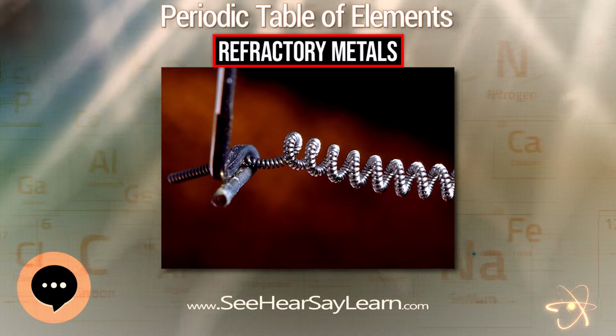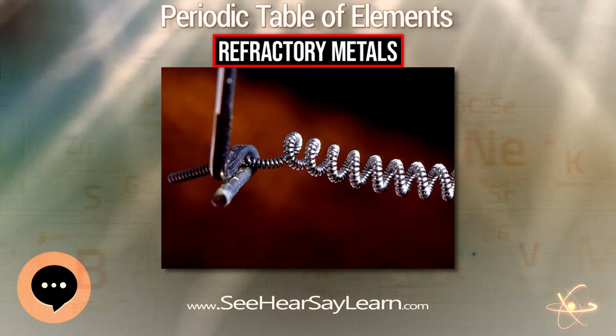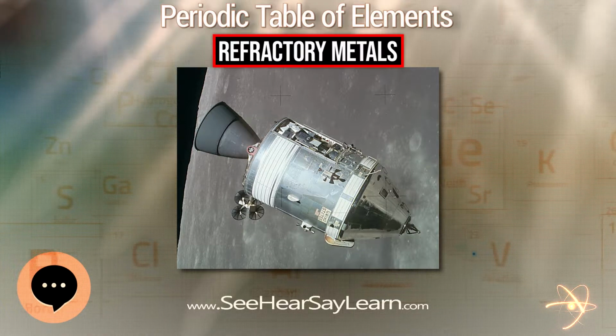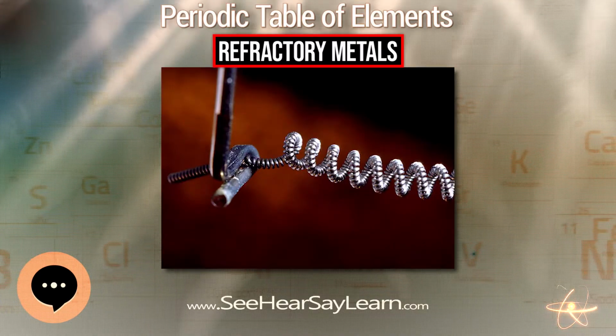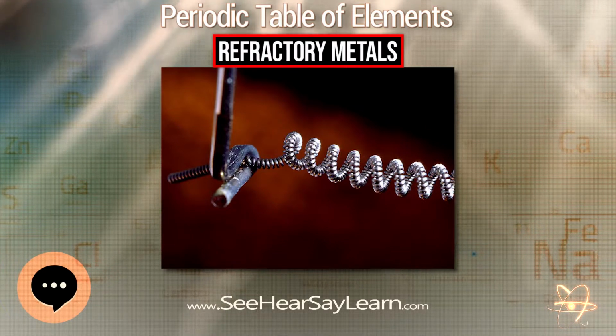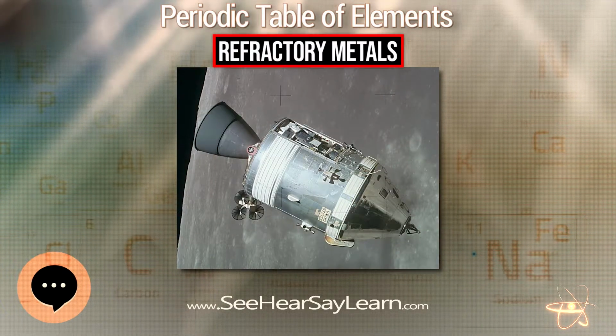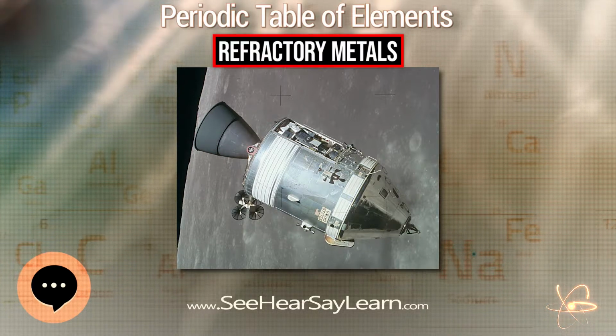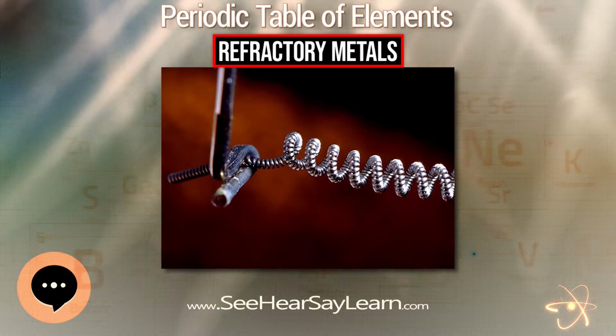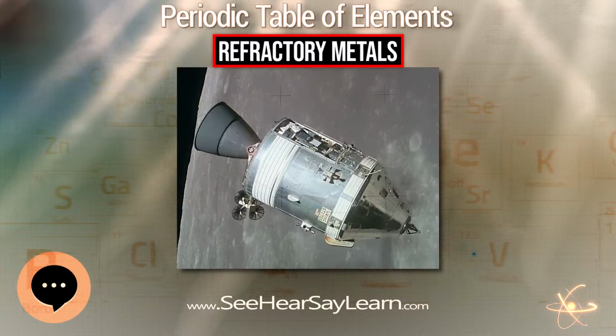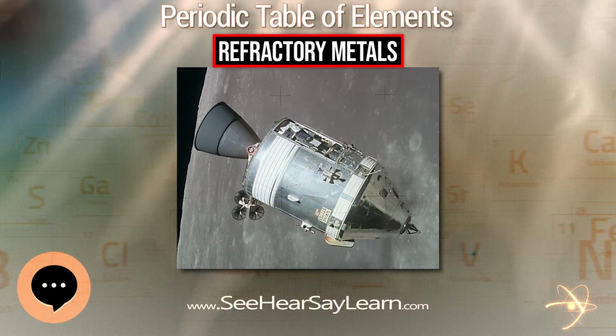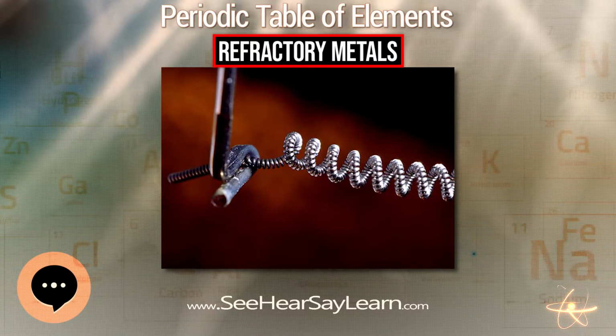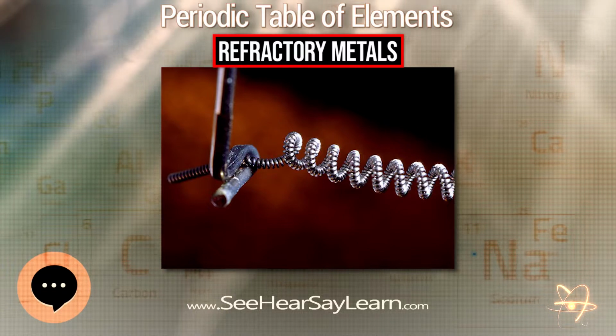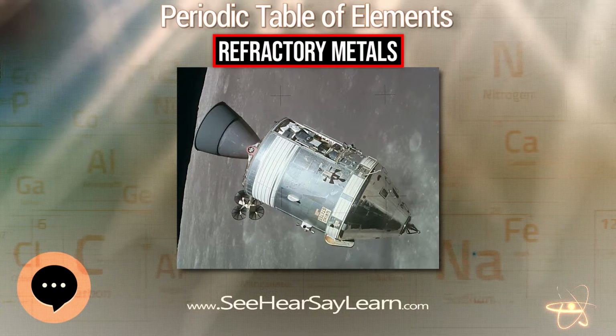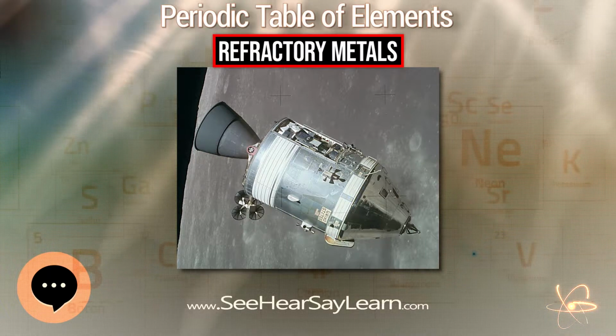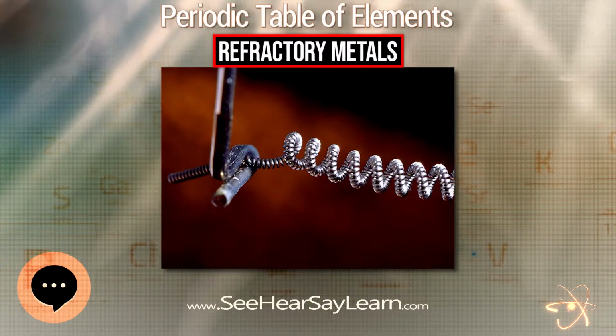All the metals are body-centered cubic except rhenium, which is hexagonal close-packed. Most physical properties of the elements in this group vary significantly because they are members of different groups. Creep resistance is a key property of the refractory metals. In metals, the starting of creep correlates with the melting point of the material. The creep in aluminium alloy starts at 200 degrees C, while for refractory metals temperatures above 1500 degrees C are necessary. This resistance against deformation at high temperatures makes the refractory metals suitable against strong forces at high temperature, for example in jet engines, or tools used during forging.